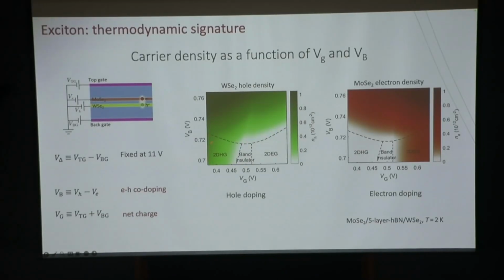So what you can see is when the bias voltage is relatively small over here, you can either have hole doping by applying a large gate voltage, or electron doping. In the middle part, nothing is doped. So you cannot have electron and hole doping at the same time. But when you apply a large enough bias voltage, then you basically shrink the effective band gap to 0. You find you have both electron and hole doping in this region and electron doping in that region. So we know that all the qualitative things are looking pretty good.